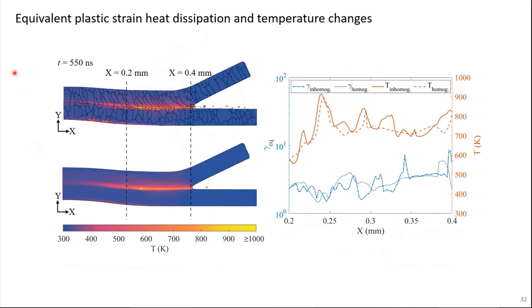So another thing we're looking at now, because we see this difference in equivalent plastic strain, is the effect of equivalent plastic strain, heat dissipation and the temperature changes. So what I've plotted over here is temperature for the inhomogeneous and homogeneous. Homogeneous basically means neglecting the effects of grains. So comparing the two, within this sort of margin, which is x equal to 0.2 millimeters and x equal to 0.4. So I'm basically looking at this region over here, and that's what we've plotted in the graph on the right.